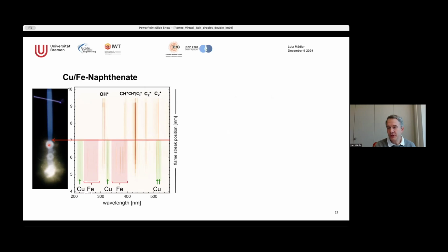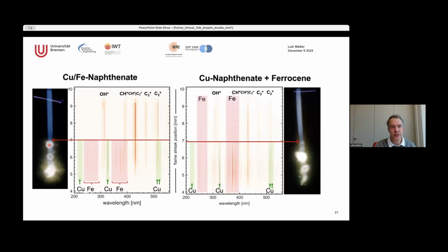If we do that a different way, we change the precursors. We use a copper naphthenate and some iron that evaporates fast. Then, of course, we see, not of course, we figure this out through some really tidy experiments. The iron comes out first and is already in the gas phase. And then the copper only comes with the actual explosion. So we would not expect that these particles are so atomically homogeneous. And I'll show you that in a second.